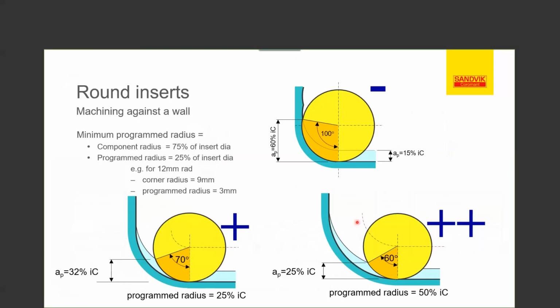So next thing we want to be mindful of is how the inserts are running. If you see here, the round yellow circle is actually your insert. Anytime we're going up against a wall, we need to be mindful that we're actually going to change that arc of engagement on those inserts. So we need to be very careful with our programming techniques. For instance, if you're coming up against a wall, you need to be cautious that as you enter this wall or this corner, and we're machining up against it, either coming down the side or coming across the floor, what's going to happen is we're going to get this wraparound effect. And you're actually going to overexert the insert. These are the areas where we're going to get a tremendous amount of vibration, a tremendous amount of heat buildup. You're going to get very ugly swarf or chips, very hard to get out of there. You're going to have challenges breaking those chips, which is already indicative of these types of materials.